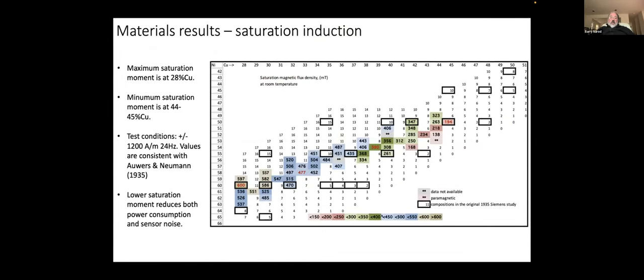Okay, saturation moment. As expected, the lowest copper content has the highest saturation moment. These numbers we have here, 600 millitesla here, 194 millitesla down on the right. Color contouring here has the red tones being the low moments and the blue tones and beige tones being the high magnetic moments. These data reflect what Auwers and Neumann found in their study pretty closely.